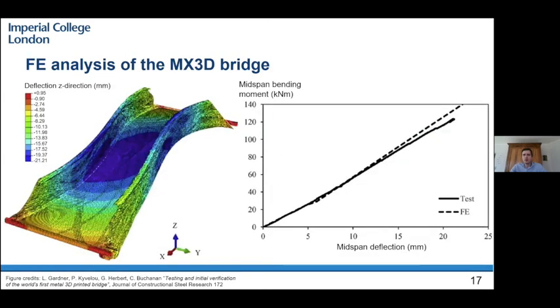Where does this all lead to? Well, the results from this thesis were utilized in the FE analysis of the MX3D bridge, the world's first metal 3D printed bridge, where the FE model didn't line up with the test results before with an isotropic material model. But after utilizing the orthotropic planar material model that was presented here and the stress ratios with the Hill's criterion, you can see, for example, on the right-hand side that the mid-span bending moment and mid-span deflections are lining up really well between the test and the FE analysis.